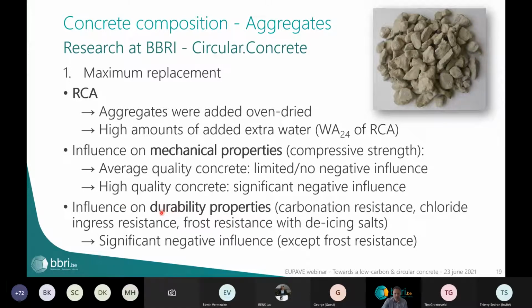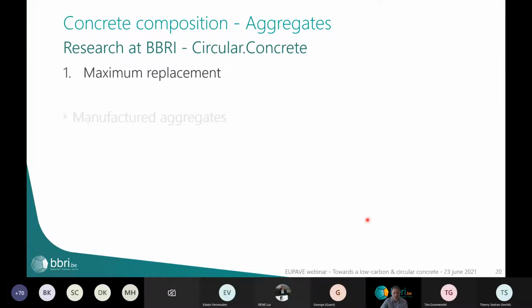And of course, there was also an influence on the durability properties. Mainly, we looked at the carbonation resistance, chloride ingress resistance, frost resistance with de-icing salts. And there we also saw a significant negative influence of the use of these aggregates, except for the frost resistance, because like we know, the frost resistance is mainly governed by the air content of the concrete, also, but more than the cement content or the water to cement ratio.